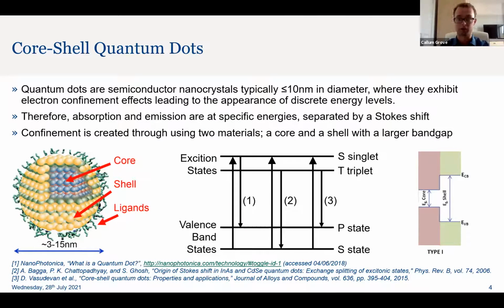So for anyone who doesn't know what quantum dots are, they are essentially nanocrystal semiconductors. They're typically less than 10 nanometers in size, and they generally have a core, shell and then ligand structure. You have a core material which has a band gap which is less than the shell, and so you end up with electron confinement within the core. The shell material surrounding it traps electrons in the core material, and therefore they produce emission when electrons are excited and then de-excite and recombine from conduction to valence.